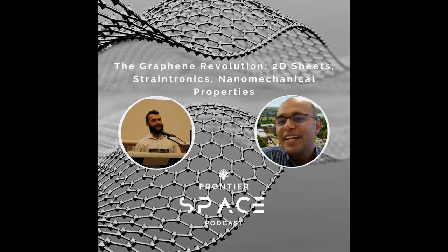Gotcha. Very cool. It's exciting research and work you're up to. And in your publication entitled "The Structural Defects of the Electronic and Nanomechanical Properties of 2D Materials," it looks like there were these things called deflated graphene nanobubbles that were important. As I said, when the material is flat, it is considered pure and pristine. With any structural disorder, bubble, or wrinkle, we have even addressed different shapes of wrinkles, like standing collapse wrinkles or bending wrinkles. We found that different shape, density, and height of these structural defects alter the electrical and mechanical properties differently.